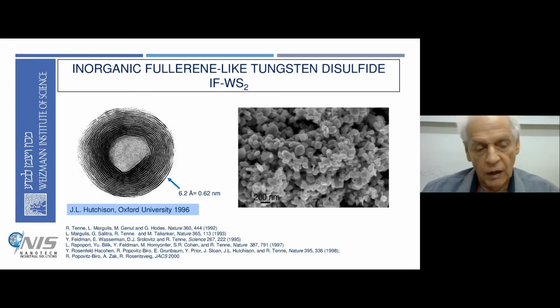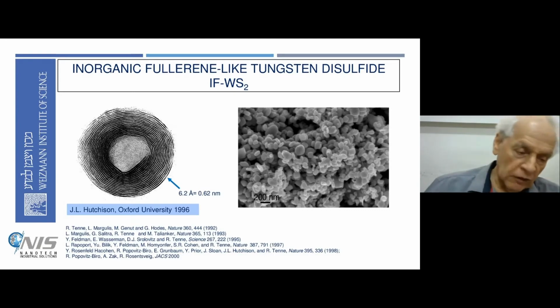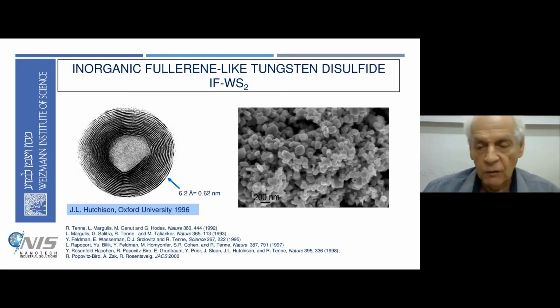It took us many years to reach the possibility of seeing these nanoparticles in a unique phase. After large effort, we were able to find the conditions, study the growth mechanism and chemistry, to such an extent that we can produce a pure phase of these nanoparticles. Remember, this is a nanoscale phase - it exists only in the nano, and no material likes to remain in nano. If you heat it up, it will always go to the macroscopic, flat platelet form.